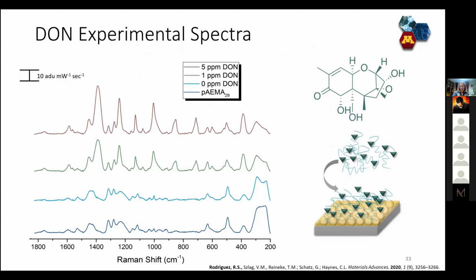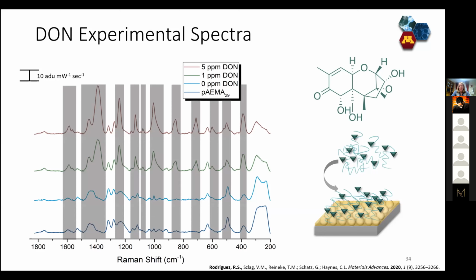We did that same selection using isothermal titration calorimetry and all the early Raman experiments. We decided that this 29mer seemed to have the best affinity, and so we put it on the substrate. The bottom two spectra you're looking at are negative controls. One is just the polymer, one is the polymer in the solvent conditions that the DON is presented in. Then the top two spectra are with two different concentrations of the DON. Even if you don't know what Raman spectra are, you can see there are lots of differences between the bottom two spectra and the top two. There are lots of really nice clear bands that show up when the DON is held close to that